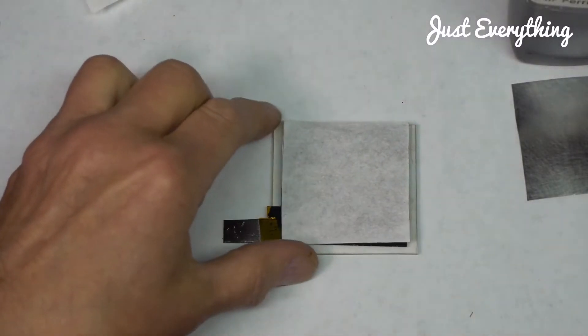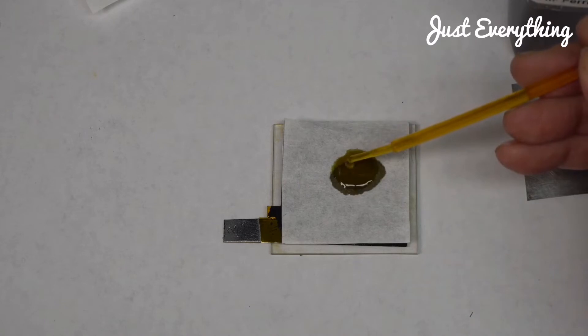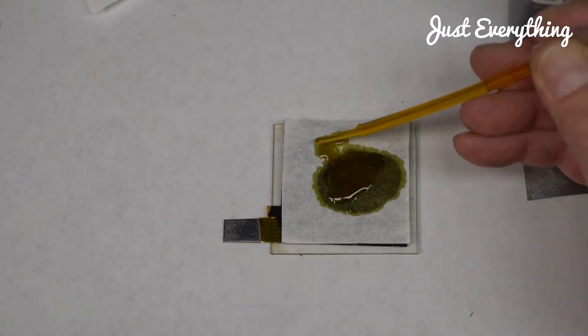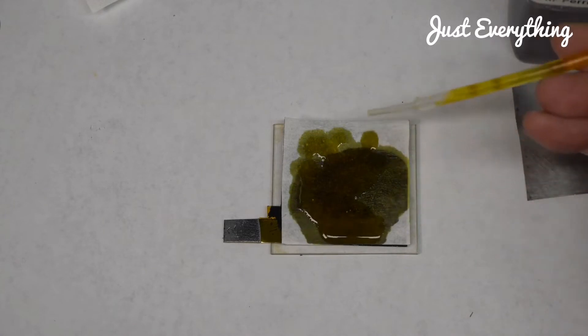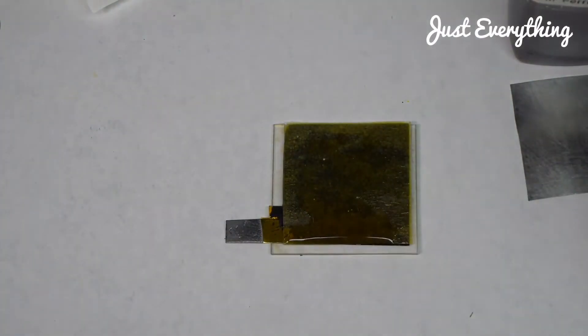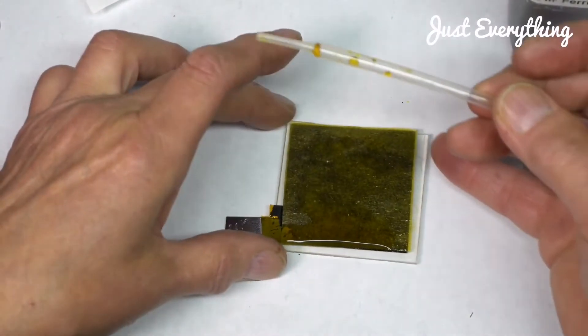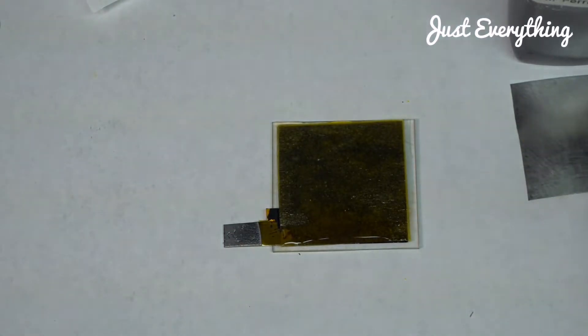Now the separator is now saturated with electrolyte, which is two molar ferric chloride. So that now is just left long enough. So both the separator and the active carbon coating is saturated with electrolyte. About 20 minutes is probably one more.